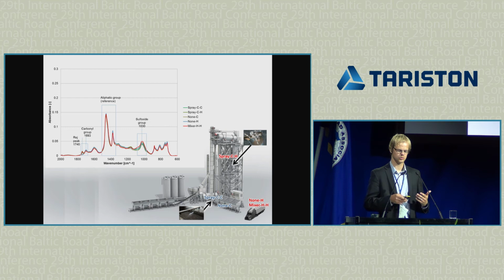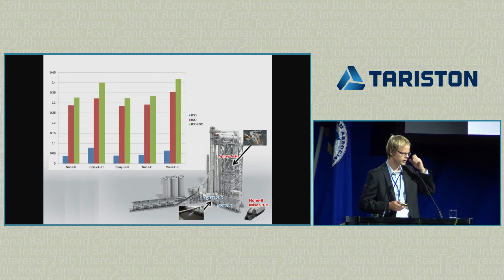But what we wanted to see is whether, based on our addition spot, the area increases in one or the other case. So to do that, we can plot the area in a chart as an index. And if we focus only on the green line, this is the combination of these 2 areas. First of all, the second group, the spray CH, which means that we sprayed the rejuvenator on cold asphalt and sampled hot, has the same index as the mixer HH, where the rejuvenator was added in the mixer and sampled hot. So there has not been additional aging due to addition of the rejuvenator before the drum.